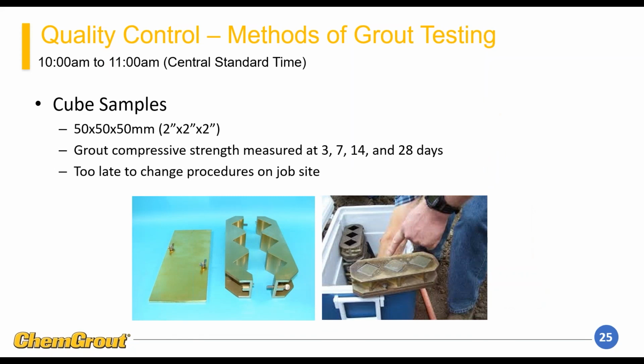A lot of the projects will require grout cubes to prove that the grout is not only mixed up in the right proportions, but the cement was not old. So they'll actually take samples with these grout cubes, and you'll set them aside, and you'll do a compressive strength test at different days during the life of that sample. So typically they'll do a break at 3 days, 7 days, 14 days, and finally one at 28 days. And that's just a final check because it's too late to change anything on the job site.